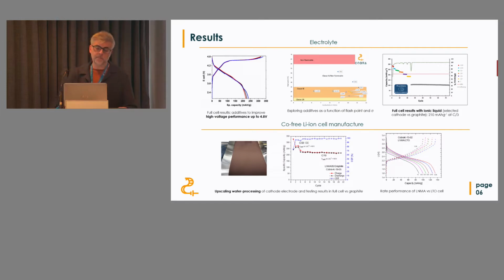These are representative figures of the profile of the cell. This is full cell results, the one that you can see on the left-hand side, on the top side. So the characteristic plateau of 4.5 volts, which is characteristic of these lithium-rich oxides.